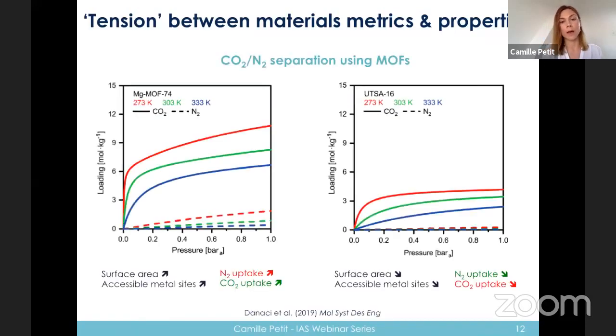But this is not that simple, in the sense that we may have tensions between materials metrics and those properties. And I take the example here of CO2 nitrogen separation using MOFs. So we have here isotherms for CO2 and nitrogen for two MOFs, MOF-74 and UTSA-16, where we have the solid line, the CO2 isotherm, and the dotted line, the nitrogen isotherm for both cases. And you can see that for MOF-74, we have a good uptake of CO2, better than in the case of UTSA-16. But we also have for MOF-74 a greater nitrogen uptake, which is a negative thing if we don't want to end up with nitrogen in our outlet stream. And so we will have to basically balance between that CO2 uptake and nitrogen uptake, something that Arvin last week referred to in his webinars as well.